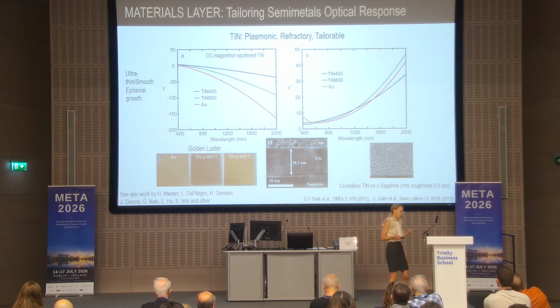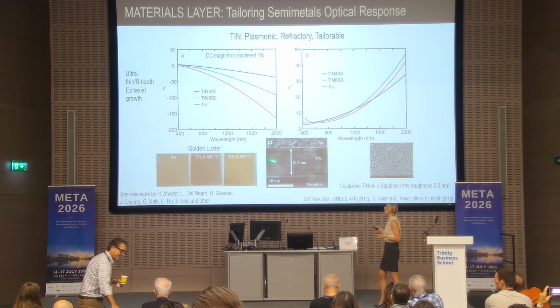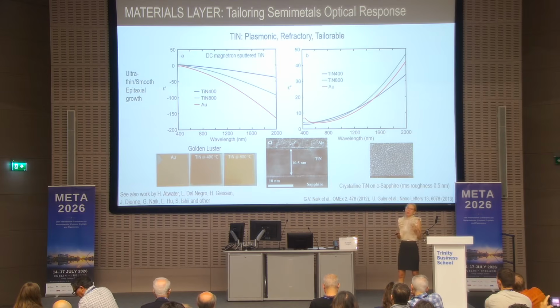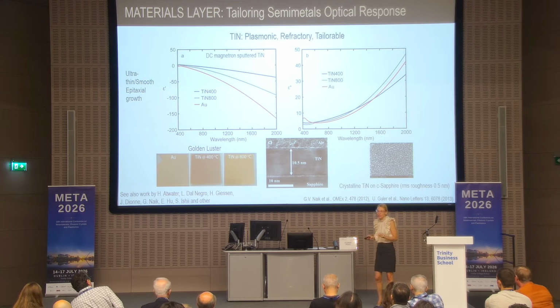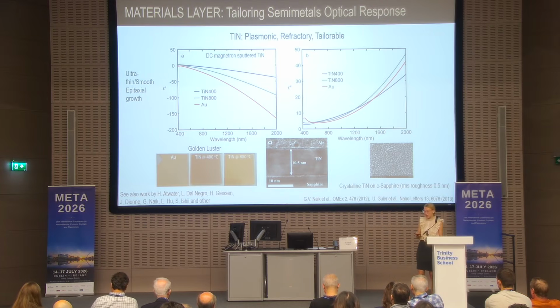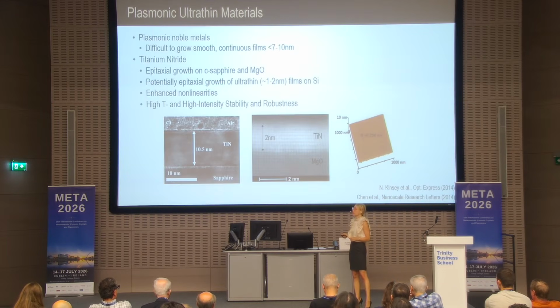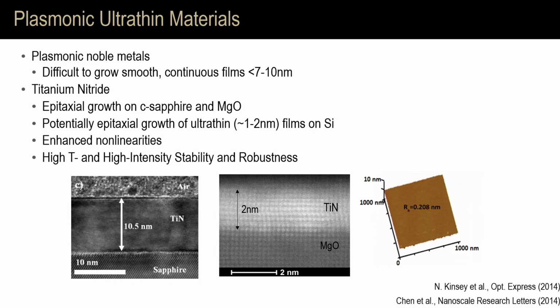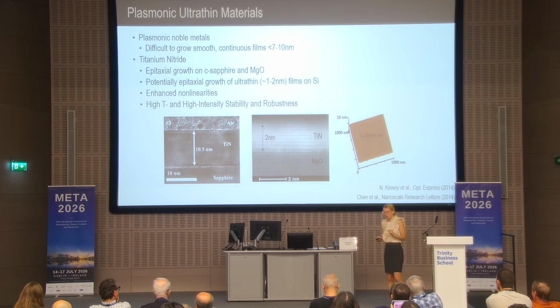The most important thing here is that with the new materials that we introduce in the area of nanoplasmonics, we open up new regimes of both fabrication and material synthesis. For titanium nitride specifically, you can grow it epitaxially on a range of substrates. Growing really thin, really smooth metallic films is difficult. Here it happens just because you have a lattice match, and it makes it possible to go down to very small thicknesses. It was predicted by many theoretical works and later shown experimentally, for example by Javier Garcia-Abajo, that if you go to extremely thin films, wonderful effects happen, simply because the metallicity of your material will change, and then you can have this tailorable or tunable plasmonic response.